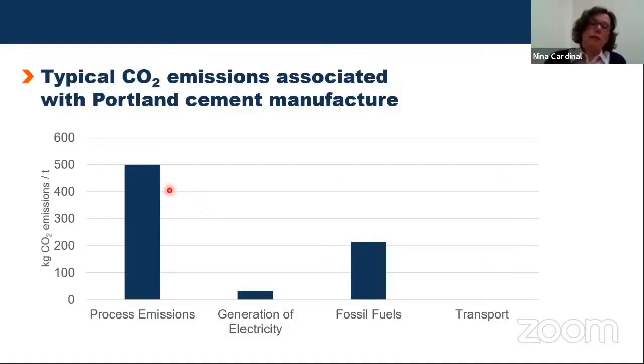This process involves a lot of heat, preheat, to pre-calcine the material, and then to heat the kiln to about 1400 degrees. And for this, we require fossil fuels. These again are associated with CO2 emissions. We also need a small amount of electricity to grind our raw mill and the clinker and to run the crusher. With regards to transport, virtually no CO2 emissions are associated with transport because we quarry our materials on the site where we also make the clinker and the cement.